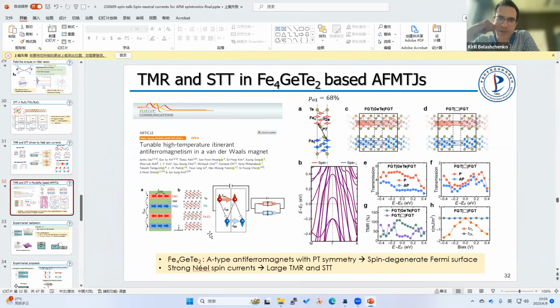So I think the situation seems clear in the case of an altermagnet like ruthenium oxide, where you have filtering by k vector, right? So your bands are spin polarized. So roughness at the interface may not fully mix them, but if you have the case like in the last example that you showed, where the bands are not spin polarized, then the matching is by different sublattices. So if you have roughness of the kind that randomizes the matching between the two sublattices, then the effect would be destroyed. So you need to have sublattice A on one side matched to sublattice A on the other side for that. Exactly.